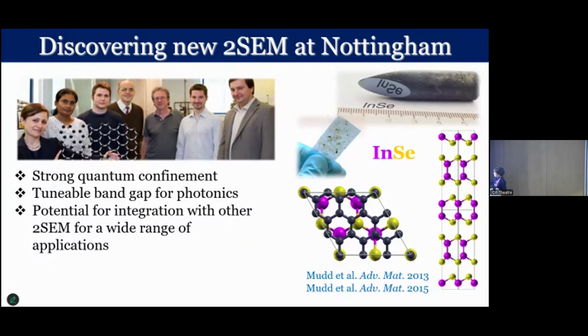And here you see a comparison of graphene and the single layer. So you see they both have hexagonal symmetry. One has a larger lattice constant than the other. And what we discovered is that it is truly a semiconductor because it has a band gap, strongly affected by quantum confinement. It is compatible with graphene, in the sense we can combine different layers,